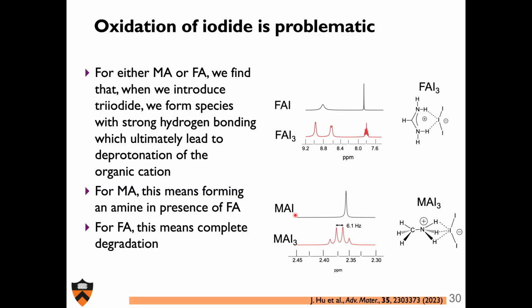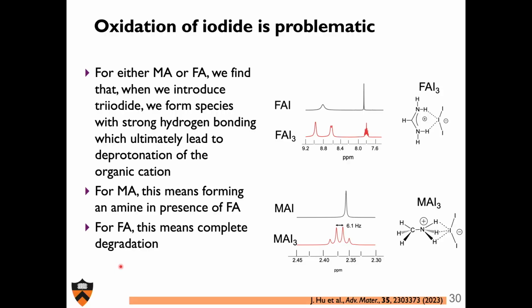And unfortunately for FA, when I deprotonate it, it's complete degradation. The products that FA deprotonation forms cannot reform formamidinium. With methylammonium, actually, if I make methylamine and HI, there's a pretty strong push toward reforming the methylammonium. But not in the case of FA. That's a one-way street to being degraded.